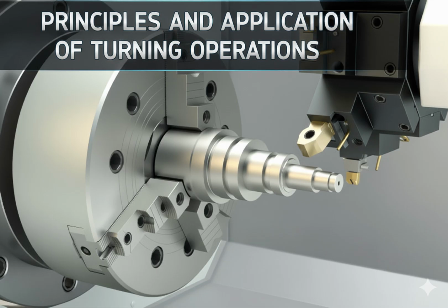The contrast is stunning. I mean, think about the easiest material to cut, something like aluminum, an ISO-N material. Your KC1 might be around, say, 350 newtons per square millimeter. Manageable. Now, try to machine that ISO-H hardened steel. What's the number? It's somewhere between 2,550 and 4,870. Whoa. It's not just a little harder. It's the difference between slicing through soft butter and trying to slice a granite countertop with that same knife.